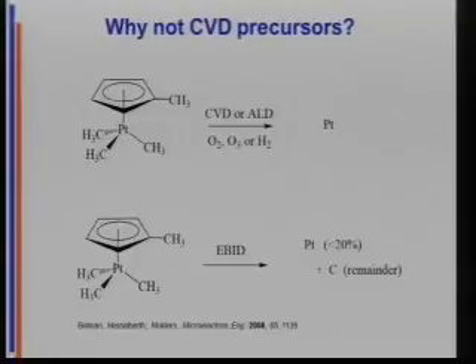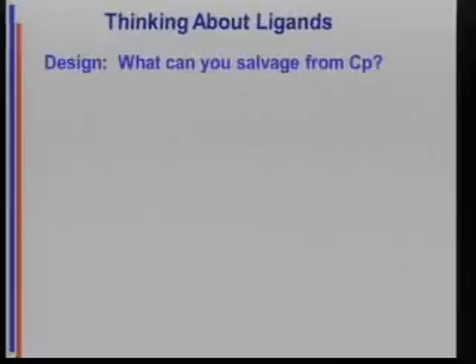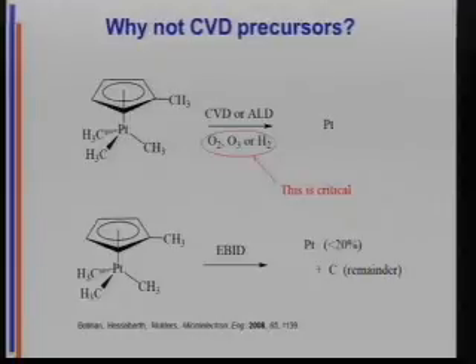And these guys call this, I love this, they call it platinum contaminated with carbon. Excellent. Okay, I call that carbon contaminated with platinum. But okay. And the reason is, this is a critical part of the CVD with that compound. It's always done either under strongly oxidizing conditions with an oxygen or ozone co-reactant, in which case you're burning off the ligand to CO2, or you're hydrogenating everything off with, platinum's a good hydrogenation catalyst. Okay. So this doesn't work well.